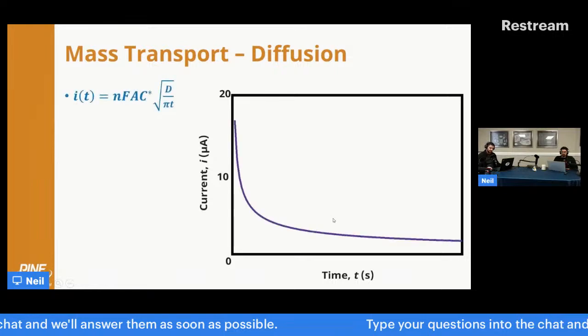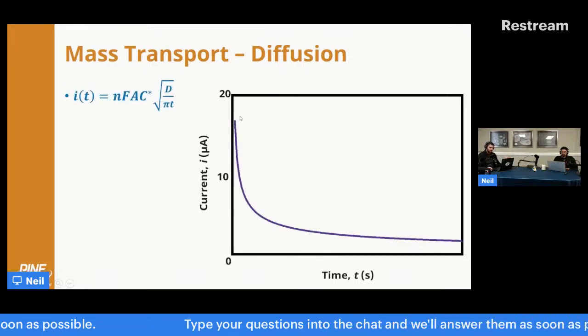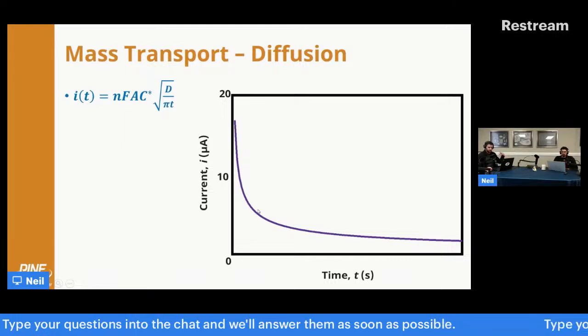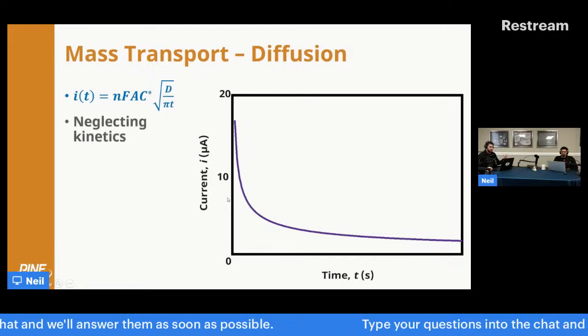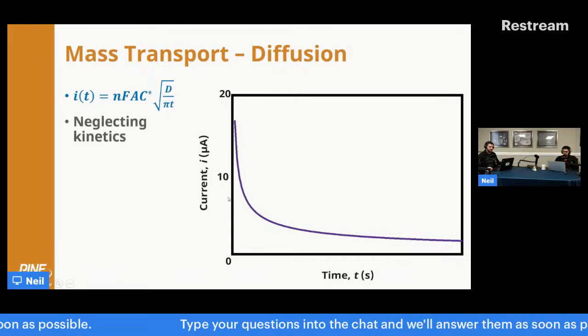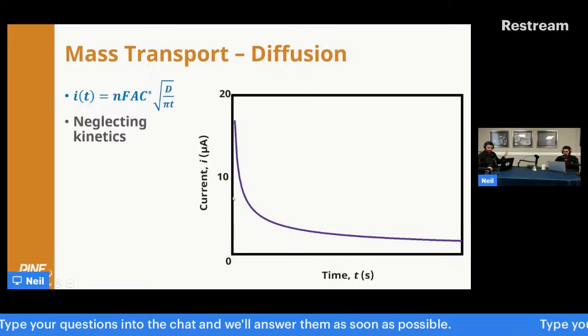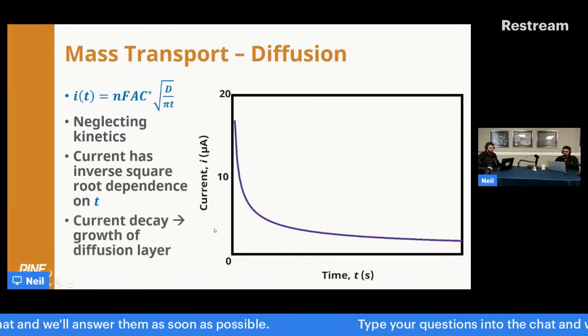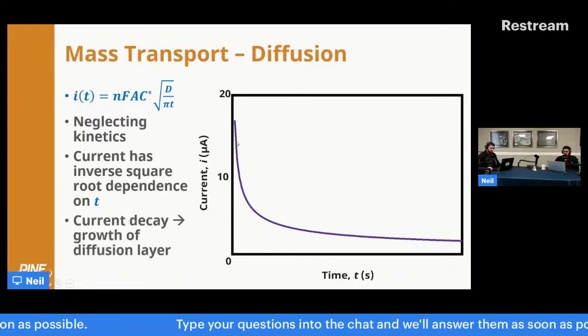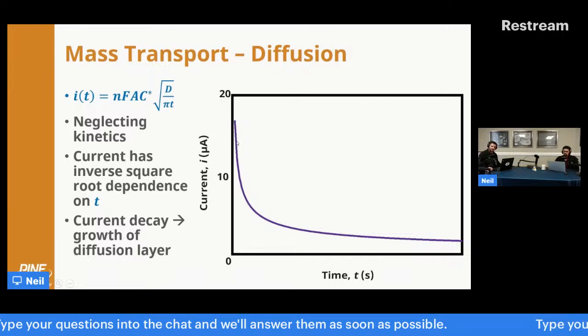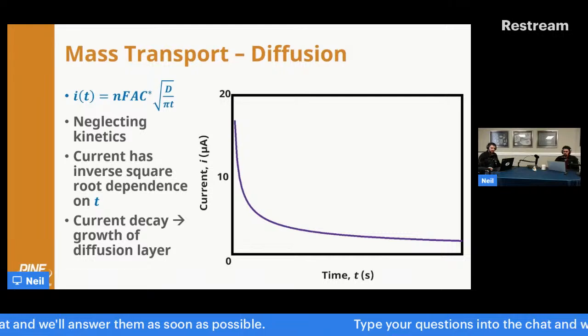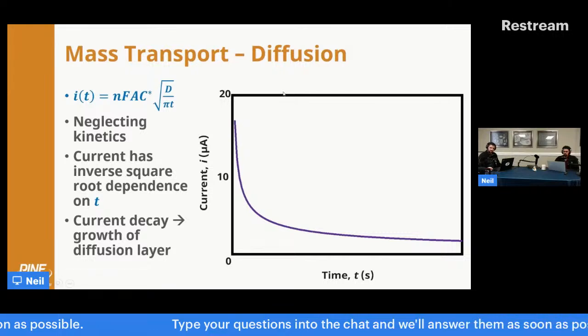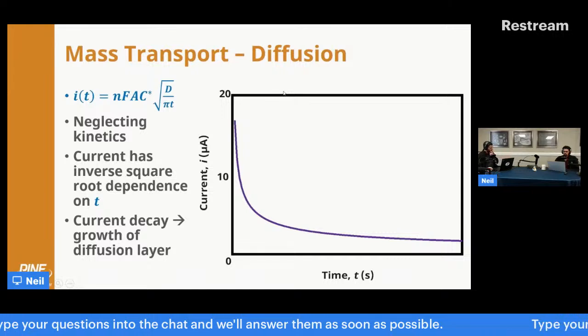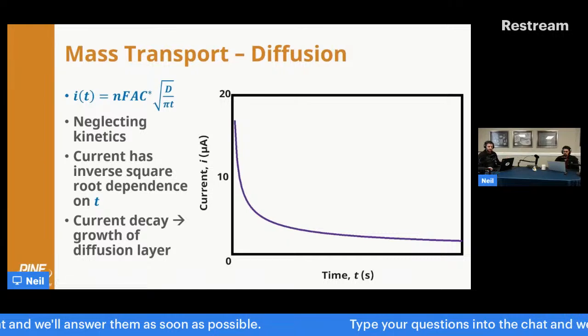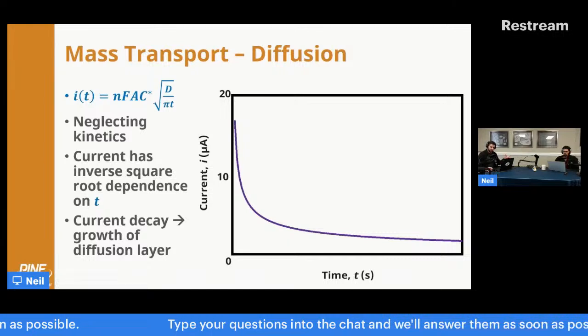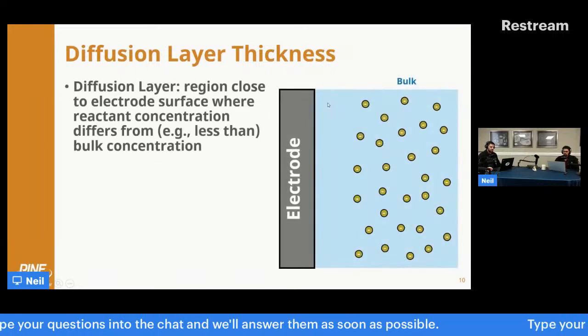When you plot that, it looks like this. It's a decay. Current versus time has a decaying characteristic as a consequence of diffusion. And this is neglecting kinetics and everything else. These are looking at each of these processes independently. Again, the physical explanation for this decay is that the diffusion layer is growing, which means the path length of diffusion is getting bigger, which means that it takes longer for materials to make it to the electrode surface. That causes a reduction in the current because there's less stuff to react. The diffusion layer thickness grows.